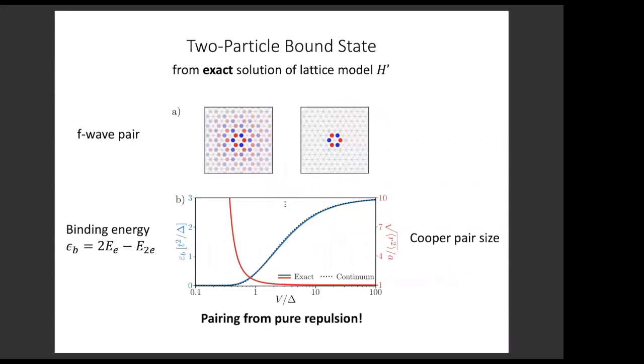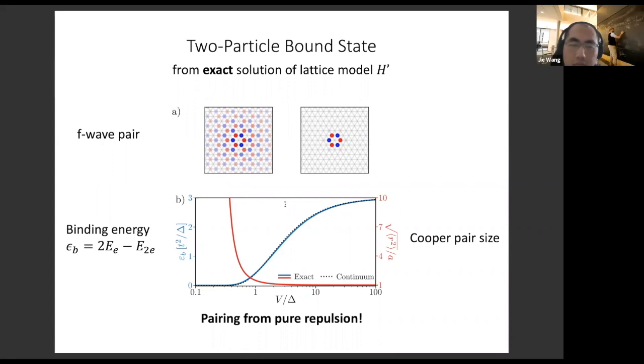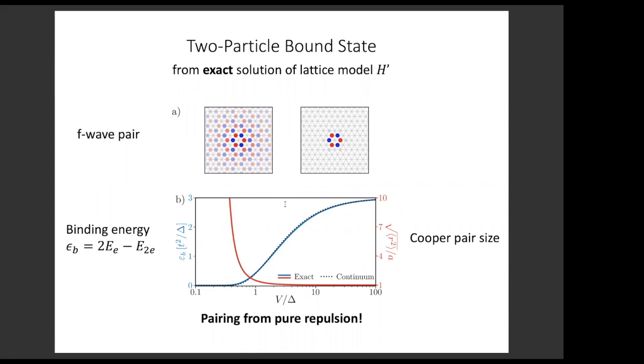Okay, so what's really remarkable is that pairing occurs right away. If you consider just 2 doped electrons, we find there's already a 2-particle bound state. This is obtained by solving the exact lattice model of the effective Hamiltonian, and we see that the Cooper pair has F-wave symmetry, and we plot the binding energy as a function of the interaction strength V over delta. As V over delta increases, the doped electrons become more and more strongly correlated. So the Cooper pair size shrinks to essentially one lattice constant at a very large V over delta. However, we're going to mostly focus on V over delta around 1, so that in our regime, the Cooper pair size is still large. So this is where we have an analytically controlled theory. Next slide.